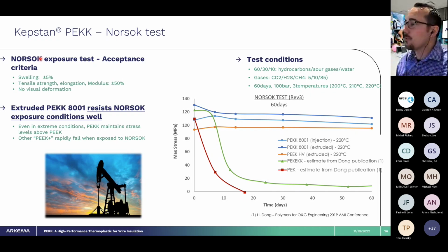Now the test itself is going to be an exposure test of hydrocarbons, sour gas, and water, where sour gas is comprised of carbon dioxide, hydrogen sulfide, and methane. The polymer is then exposed for 60 days at 100 bar at 3 different temperature conditions: 200, 210, and 220 degrees C. This is a really aggressive test, combining a variety of different treatments or exposures - temperature, pressure, and chemical, all attacking this polymer.